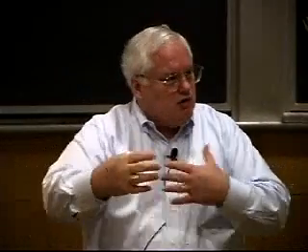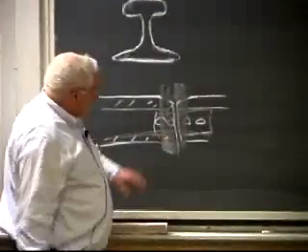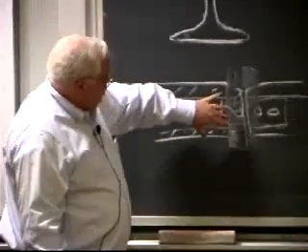One is basically a forge welding process where they take a bunch of oxyacetylene torches, just big flames, and heat up the rail for about a foot on either side until it's glowing red. And they have this big hydraulic ram. It's not a friction welding machine, it's a forge welding machine, and they just ram these two pieces of hot steel together. And they get flash, and they just extrude the hot ends out. It's hotter right at the ends. They place the flames so that you get the greatest heat right where you want it, and you have a temperature gradient back here.